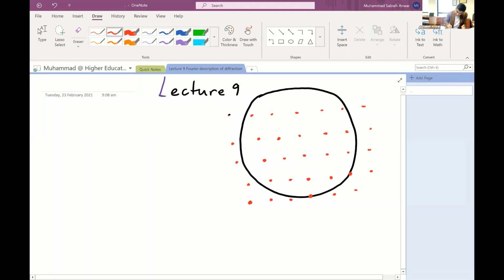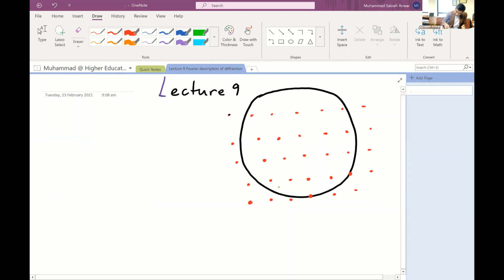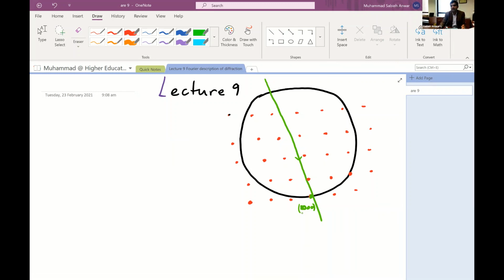Here you go. And then I draw the direction of the incident X-ray, which passes through a particular point, which I call the 0,0,0 point, which is the origin of my reciprocal lattice. And then I scan the surface of the Ewald sphere and see whether the Ewald sphere touches any other reciprocal point. So in this case, it touches a reciprocal point over here.